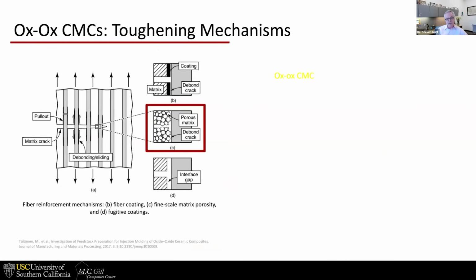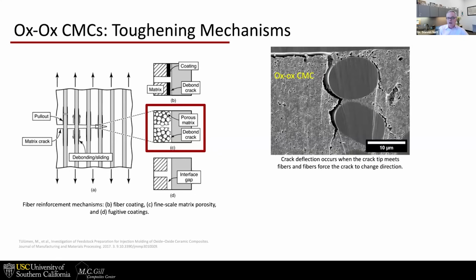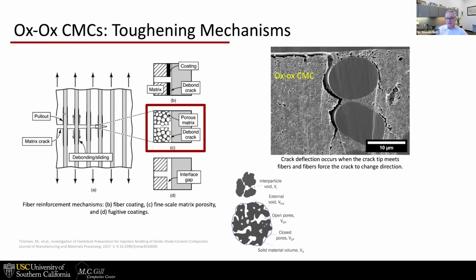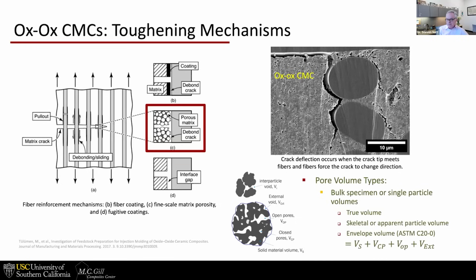And so you can see, tuning the interface microstructure and properties to achieve this type of behavior is critical to imparting toughness. Here's an example of a crack in an oxide composite deflecting around fibers. And that's actually a good thing. You want that type of behavior. Porosity is, though, as it turns out, a difficult thing to quantify. A single number doesn't adequately characterize porosity. You can say, well, the porosity is X%. That doesn't begin to tell the full story because there are different types of porosity, different shapes of pores, different sizes, different locations, and it's a big undertaking, but yet it's important.